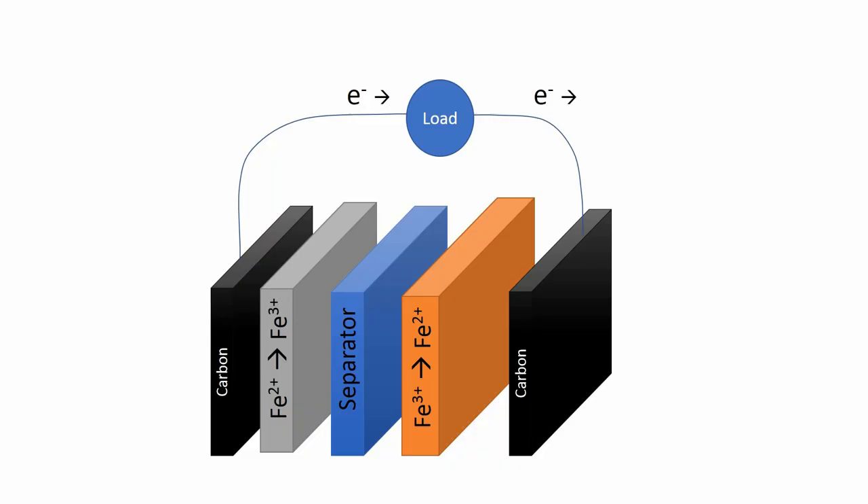So we made a hydrogel polymer of acrylamide and acrylic acid and we tested it in a concentration cell. It looks like this: on one side of that cell iron 2 is going to go to iron 3, and on the other side iron 3 is going to go to iron 2. It is a very low capacity, low voltage cell, but it should let us test how quickly that separator allows the cell to just leak and discharge itself.